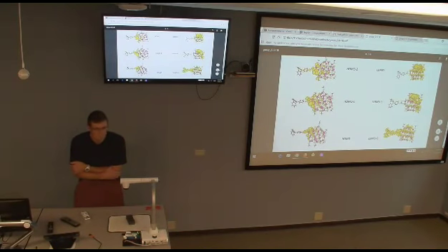But how quickly it goes, like in terms of does this help charge transfer to a dye? I would say probably you need at least a few hybridized states. The best scenario would be if you have the lowest state being more localized, and HOMO-1, HOMO whatever, are kind of hybridized states. Then they will be coupled strongly with your pure quantum dot where you excite, right? But then due to this hybridization, they will be coupled to this very localized dye state. And you probably expect that this scenario will be really facilitating charge transfer and charge separation.